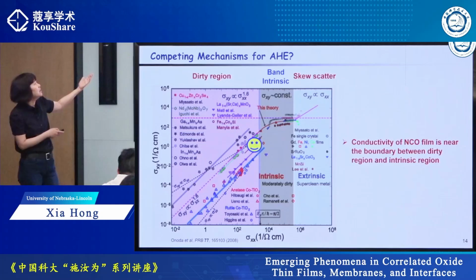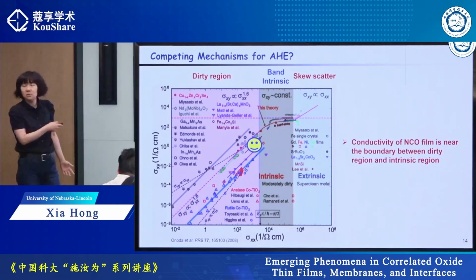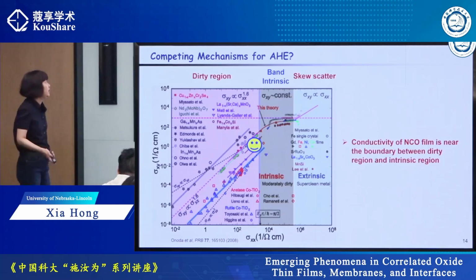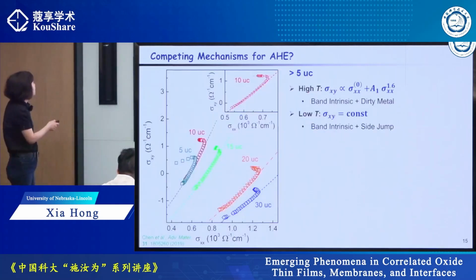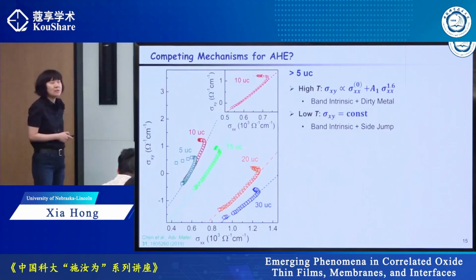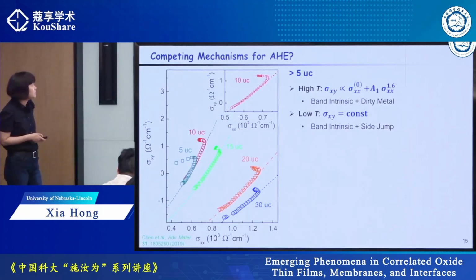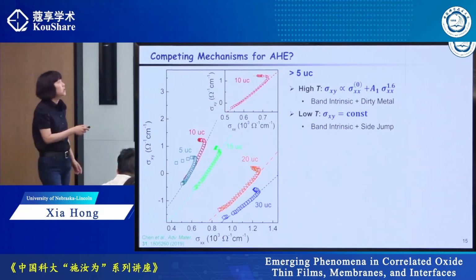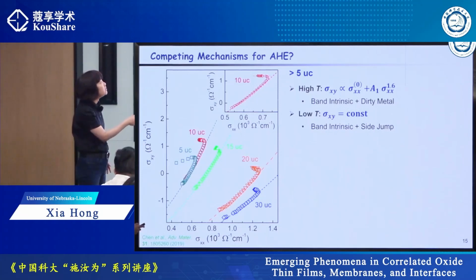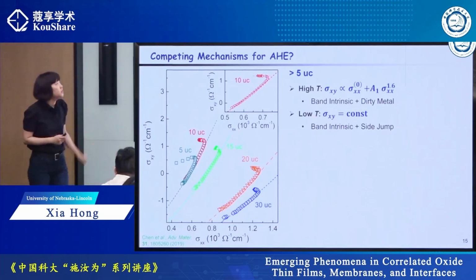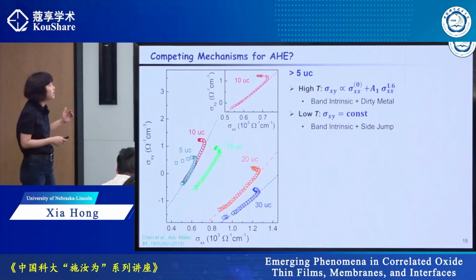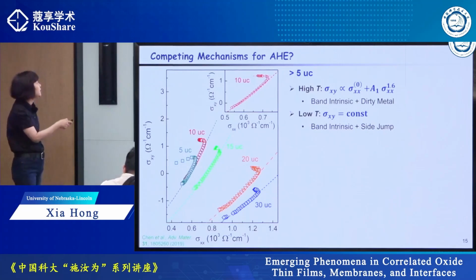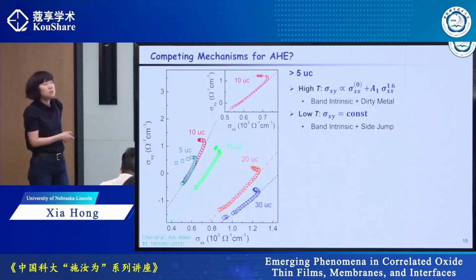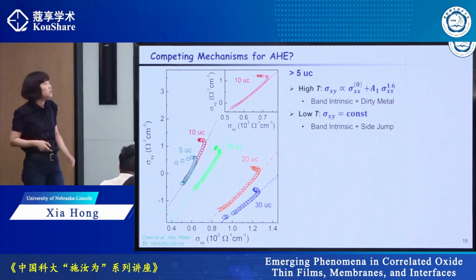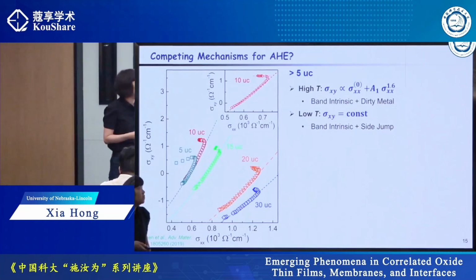So our hypothesis is you can actually add up these two contributions and see if it can fit, right? So indeed, that's what we do. We try to scale sigma xy as a function of sigma xx for our samples. And for the high temperature region, for all the thicknesses, we can use this very simple scaling behavior, two contributions. One is a constant due to Berry phase effect. The other one is due to the impurity scaling behavior with exponent 1.6, and it fits very well. Only at low temperature, we have a constant. So this is either due to band intrinsic effect or side jump.